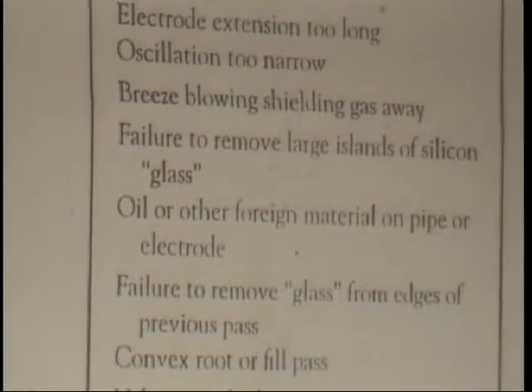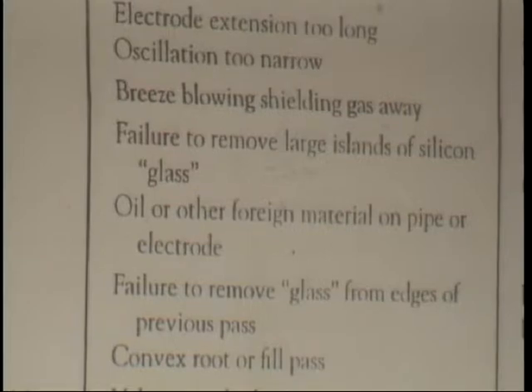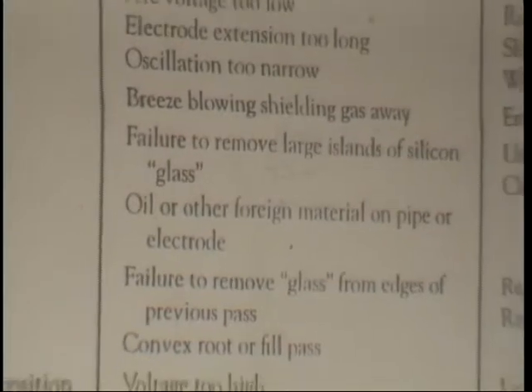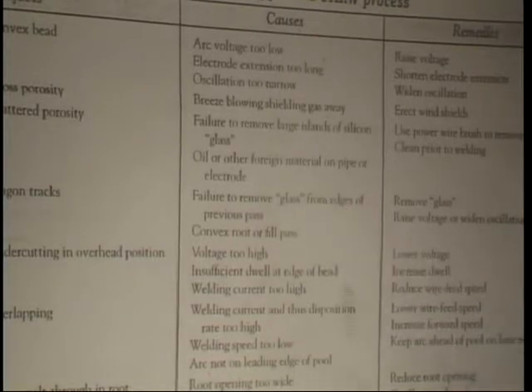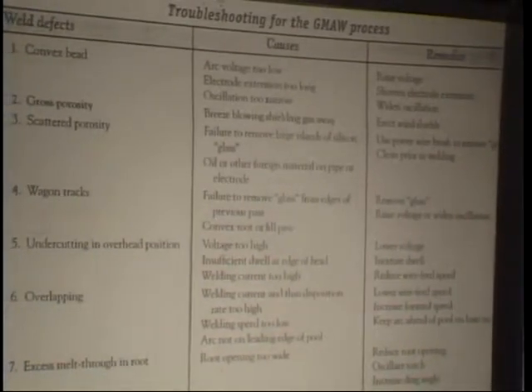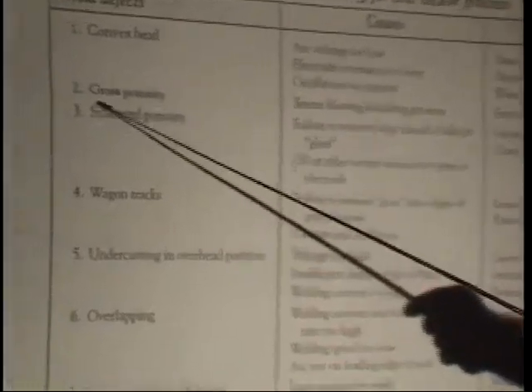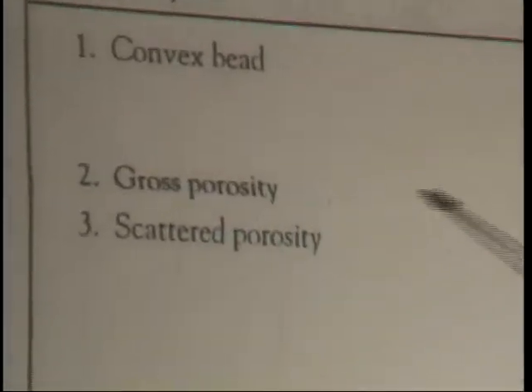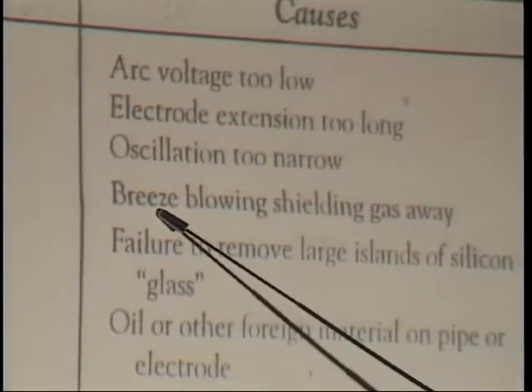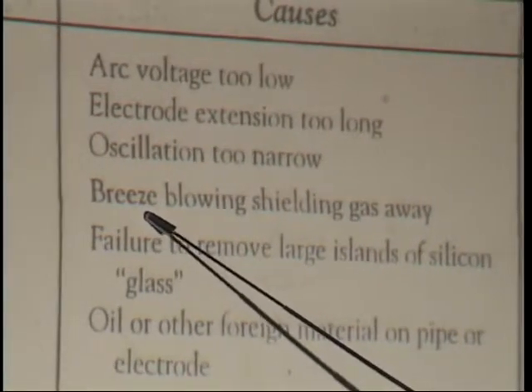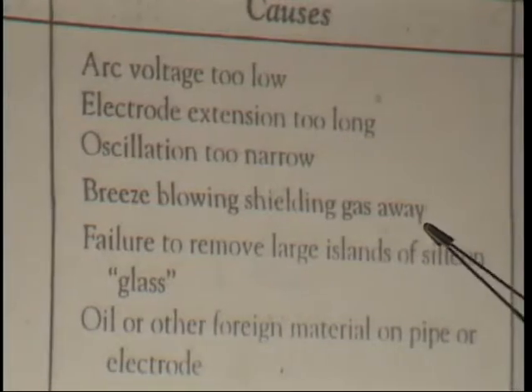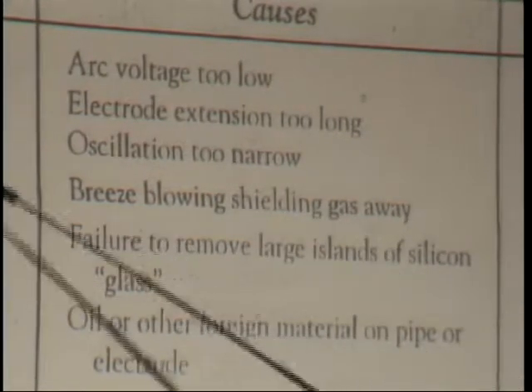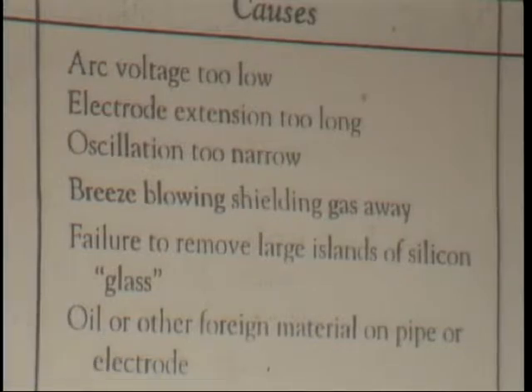And also you got to remember that those electrodes, those spools of wires, they sit on those machines for a long time, and they collect dust and other particles, and that can be dragged into your liner and then eventually deposited into the weld, and that can cause porosity. Gross porosity would result in cluster porosity. That would be due primarily to a loss of your shielding gas. This troubleshooting guide says breeze blowing shielding gas away. So that would be another one that cluster porosity would be caused by losing your shielding gas. Scattered porosity is oil and foreign materials.